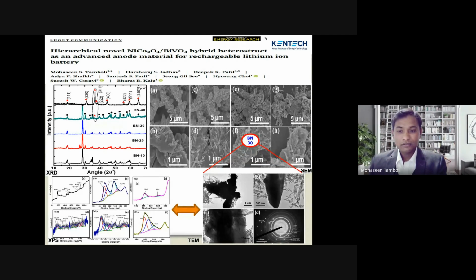So here you can see that as the concentration of NiCo2O4 in BiVO4 increases, the size of the nanowires is reduced, maybe due to the higher concentration of NiCo2O4. But if you look at figures C and F, they show a uniform distribution of nanowires on the dendrite structures. And this is actually the optimized sample of our materials.